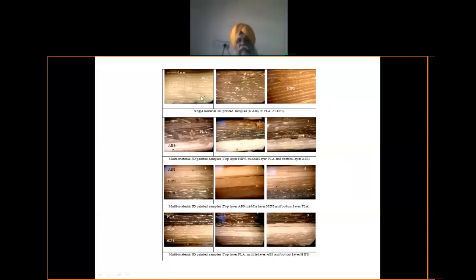So the material was printed layer by layer, but there were some asperities, or what we call the staircase effect. For the PLA it was also there, for HIPS it was also there. But once we have a lower layer of ABS and then apply a PLA layer over it, what we observed was that the liquid form of PLA, once it was deposited, was coming out in a globular form. That means here the strength is going to be less, right? So this was observed in different observations.